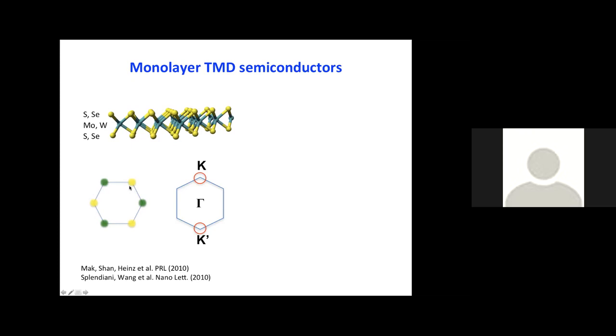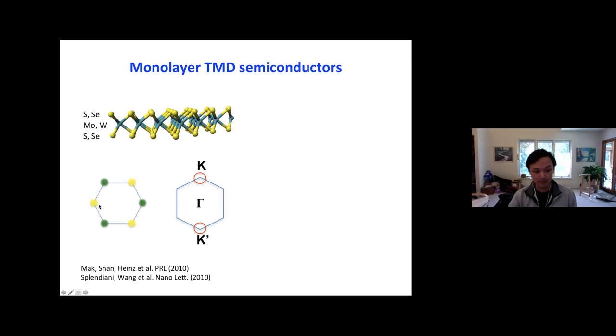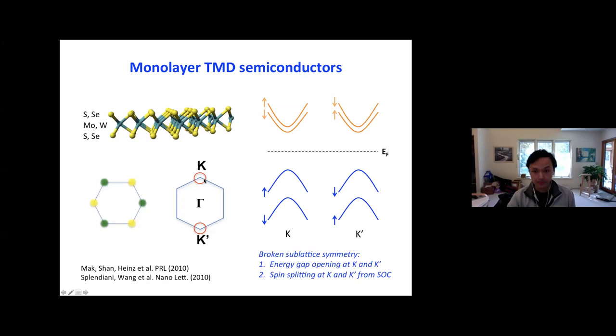So inversion symmetry is broken and energy gaps are open at the K and the K prime point of the Brillouin zone. And very simplified, a band structure of the material is something like this. In the pristine form, the Fermi energy is located inside the big energy gap. Typically, it's about 1 to 2 electron volt. And so it has two copies of direct energy gaps at K and K prime. They are related by time reversal operation.